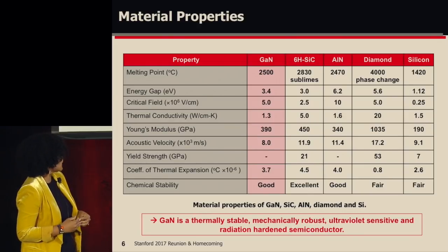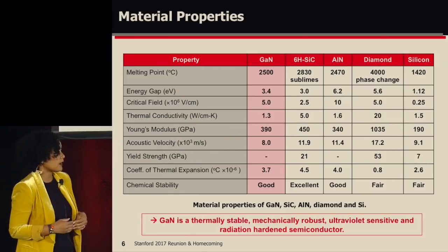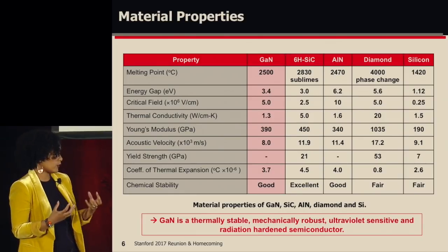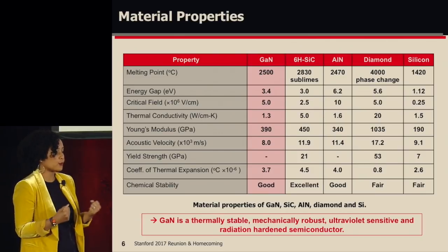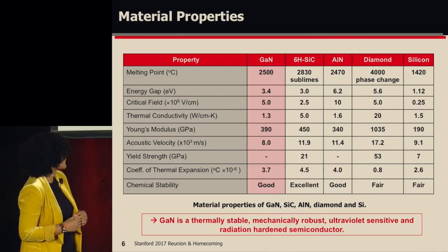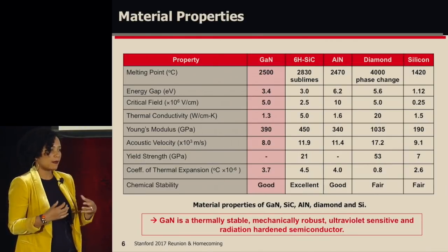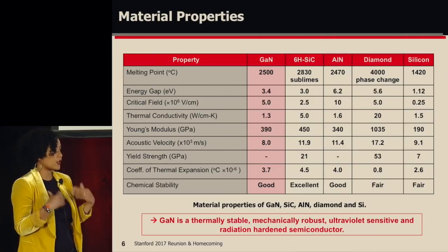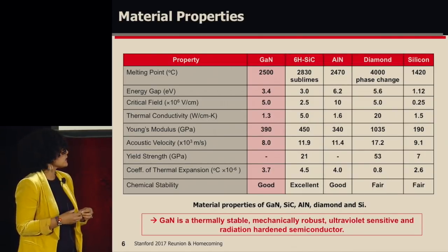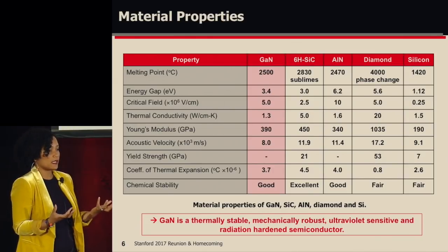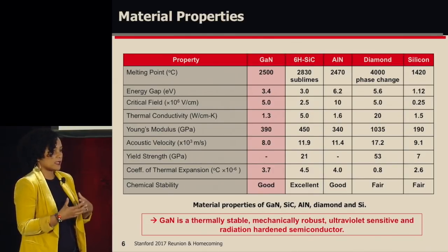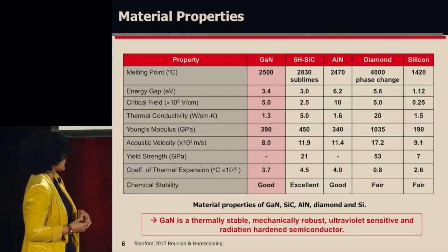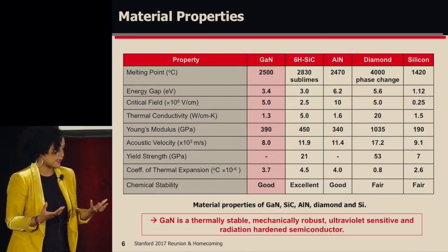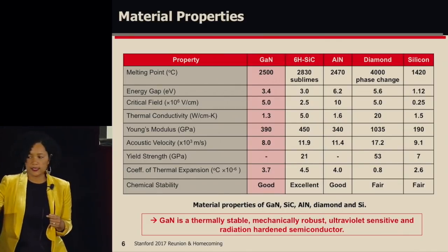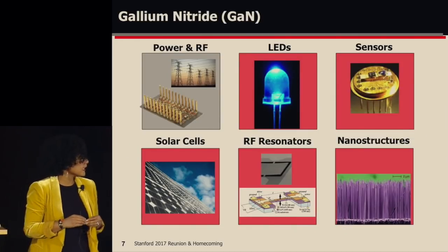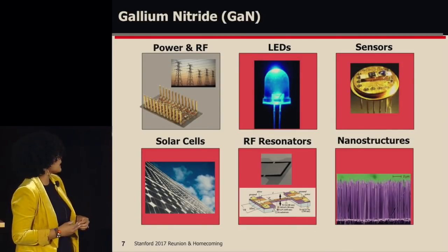What's attractive about gallium nitride is that it has a very high melting point, 2,500 degrees Celsius. So thermally, it's very stable. It takes a lot of energy to break apart the gallium and nitrogen bond. In addition, it has a very high energy band gap. It takes a lot of energy for thermal electrons to jump the valence band, and therefore it can work up to 1,000 degrees C before thermal runaway starts to dictate the electron transport in your electronics. Also, due to the band gap, it's sensitive to the ultraviolet regime, which is very advantageous in optical imaging in space.